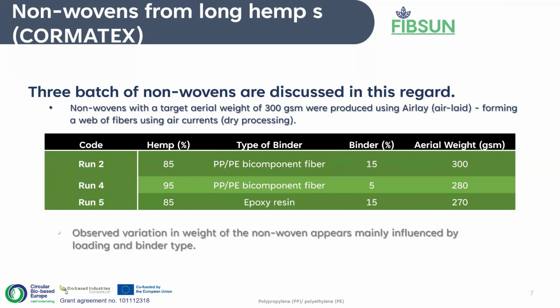And in the third case, we used epoxy resin, and this is a bit different from the PP/PE bicomponent fiber, because in the case of bicomponent fiber, as the name suggests, we have our hemp fibers, then we use a binder which is also in a fibrous form. In the case of epoxy resin, we use epoxy powder. The process is more or less air laid, which is a dry process for forming non-woven material.